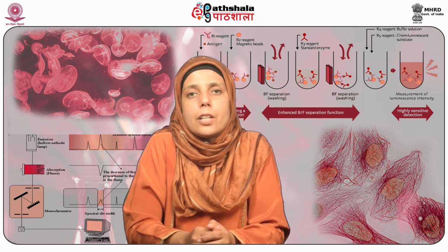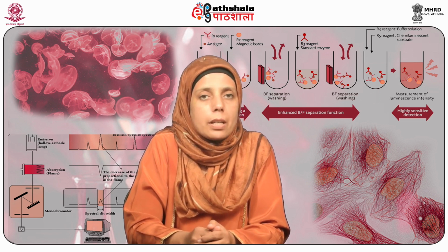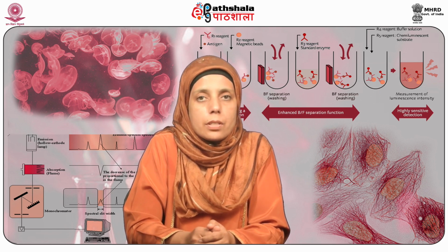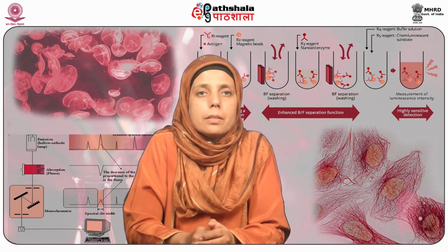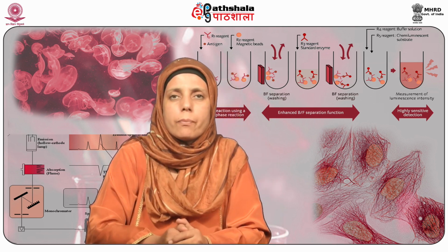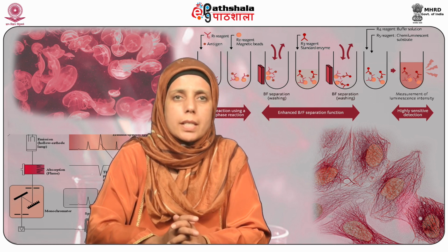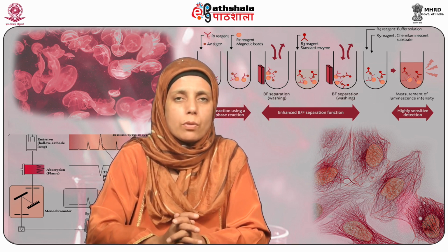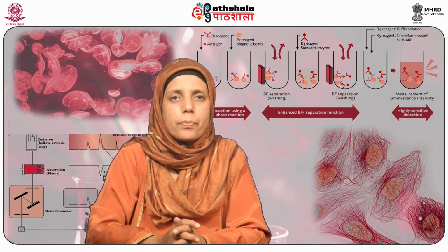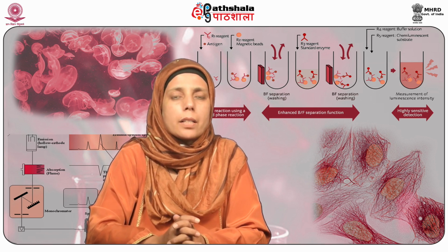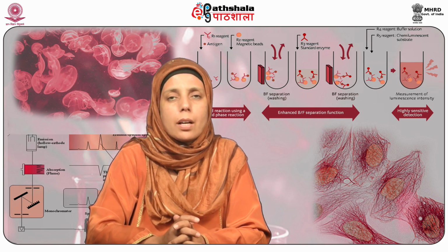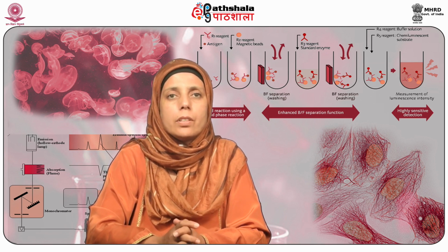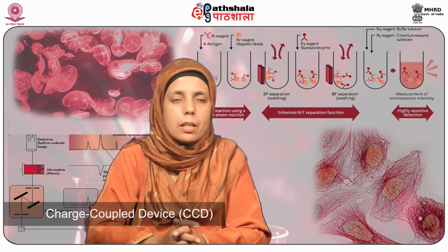The advances related to optimization of experimental conditions, interferences by molecular spectra bands or by coexisting elements or background have also been done. Sensitivity has improved, even for some hard to excite elements such as hafnium and tungsten. A low cost and compact arc optical emission spectrometer has been achieved by using a handheld spectrometer with a charge coupled device as a detector.